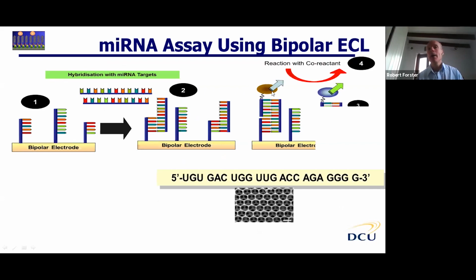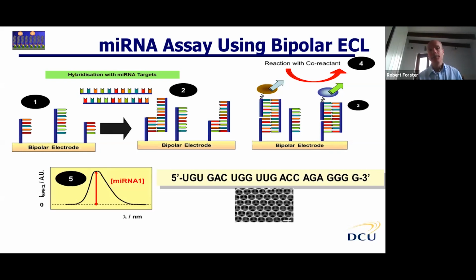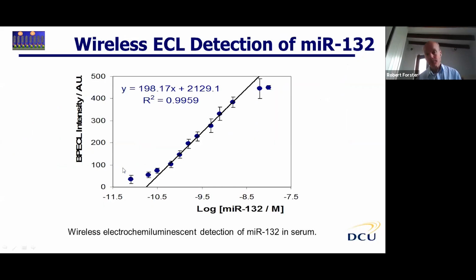And now when we use the bipolar setup, we turn on the electric field, which will oxidize that dye. When the co-reactant is present, we can now generate light. And that's shown here—we get a bright emission only when our target is present.